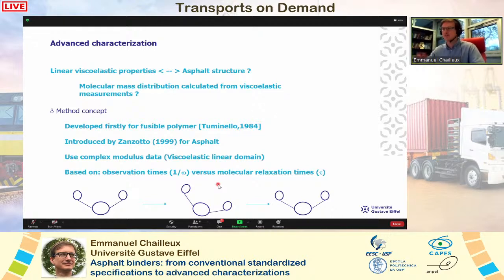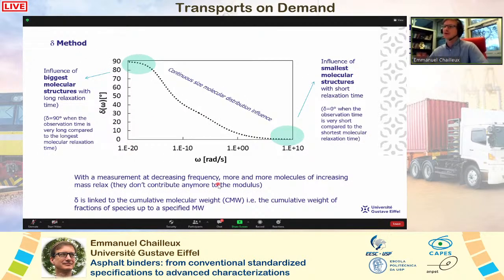So let's go more in detail, showing you a plot of phase angle according to frequency. So it is the master curve. I can go later during the questions on the master curve construction. So you see that we have a phase angle from 0 to 90, so from the elastic state to the liquid viscous state. And you see that we have a continuous curve linked to the continuous size molecular distribution influence. We think that we could represent all this behavior of this phase angle with a typical type of molecule.